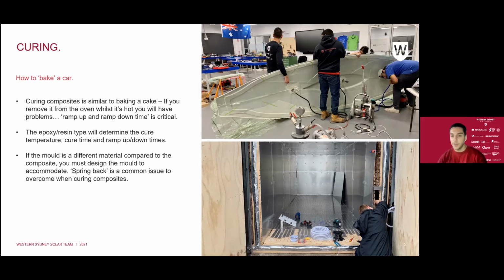So if you haven't already noticed, the last vehicle we created, Unlimited 3.0, is pretty long. It's just under 5 meters, in fact. And that really set us with a challenge as the entire shell was cured in one piece, and ovens generally don't come that big to consumers. So we had to innovate, and we ended up purchasing a shipping container and converting that into an oven that was up to the task.